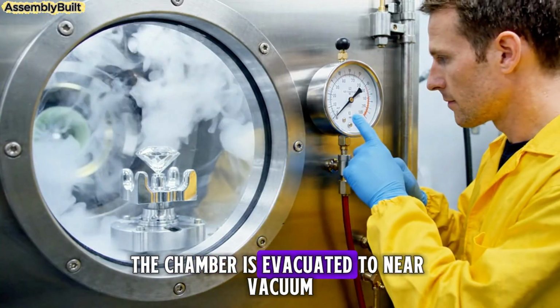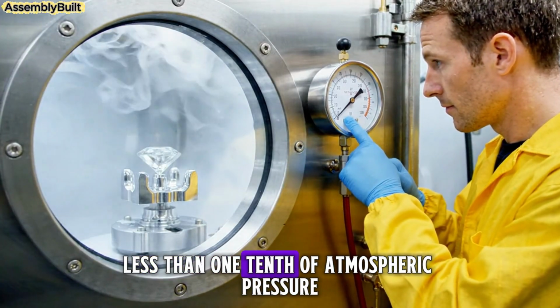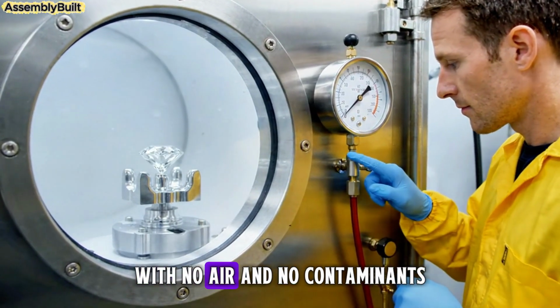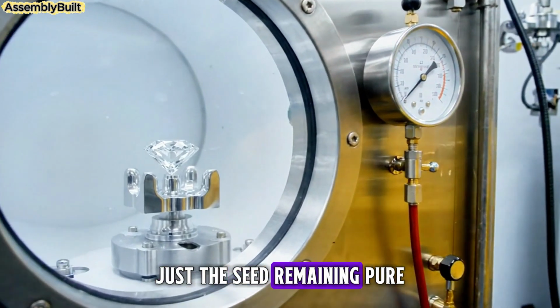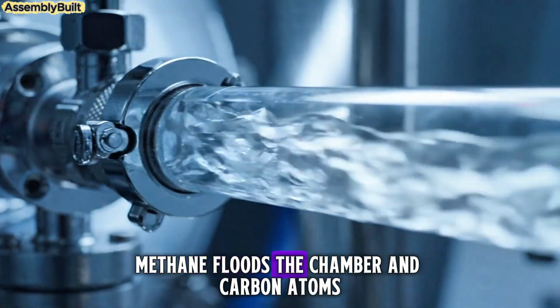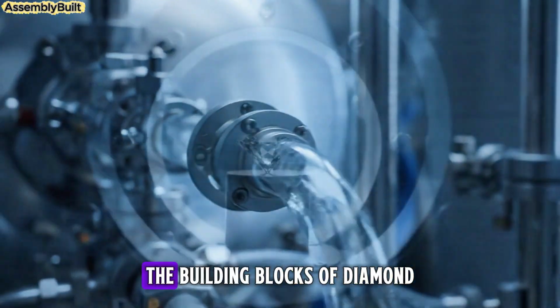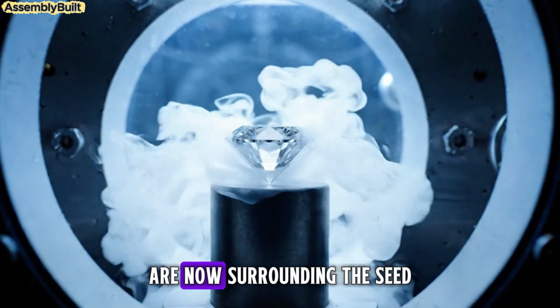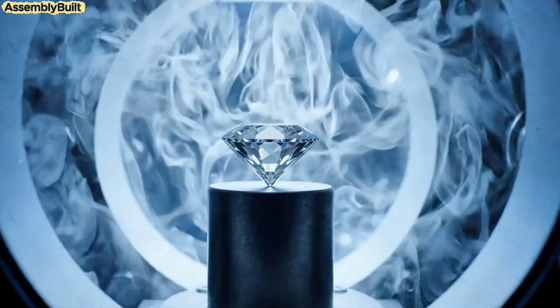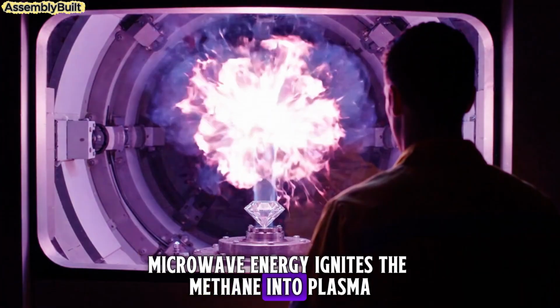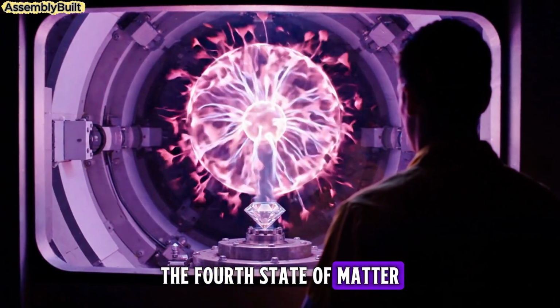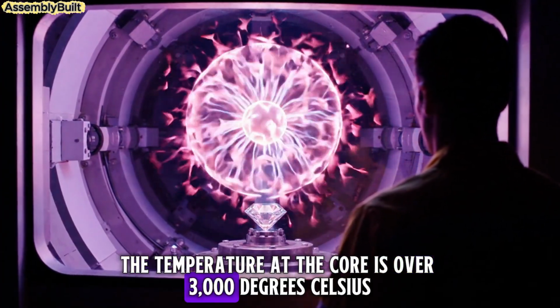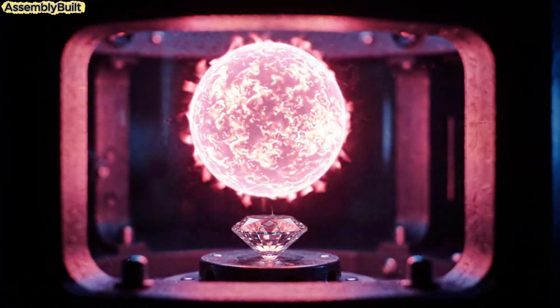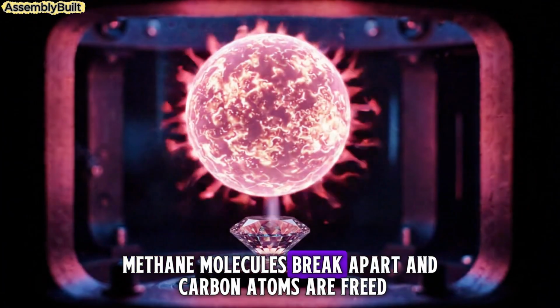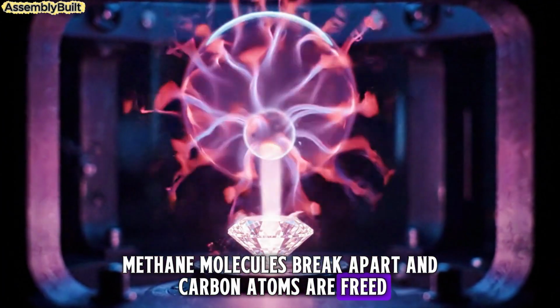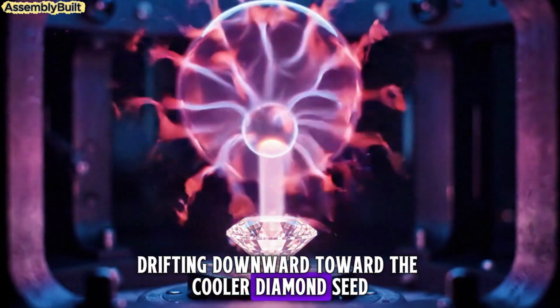The chamber is evacuated to near vacuum, less than 1/10 of atmospheric pressure, with no air and no contaminants, just the seed remaining. Pure methane floods the chamber, and carbon atoms, the building blocks of diamond, are now surrounding the seed. Microwave energy ignites the methane into plasma, the 4th state of matter. The temperature at the core is over 3,000 degrees Celsius. Inside the plasma, methane molecules break apart, and carbon atoms are freed, drifting downward toward the cooler diamond seed.